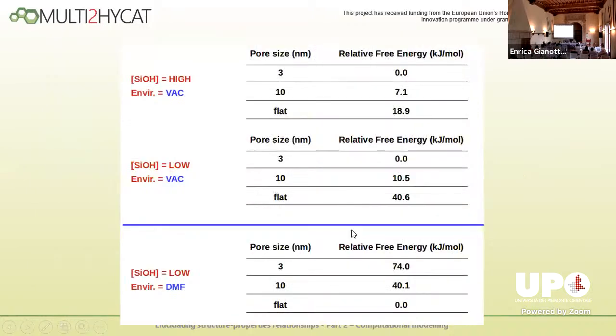At the end, what you get is this kind of result. We can compare the free energy of adsorption, of linking of the molecule, in different porous silica with narrow or wide pores or on flat surfaces. And so we could give our colleagues some information about the relative stability of the system depending on the size of the pore in the silica system.